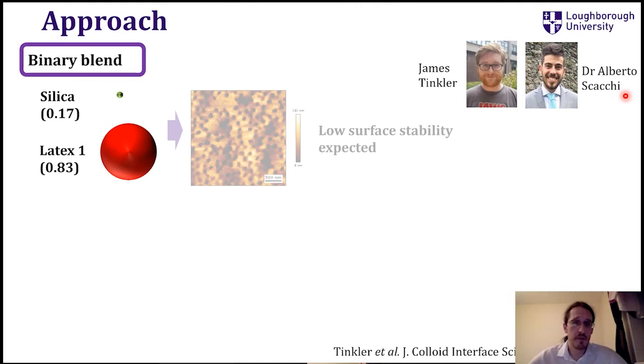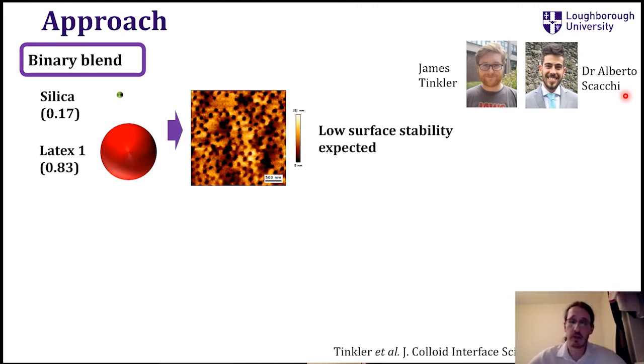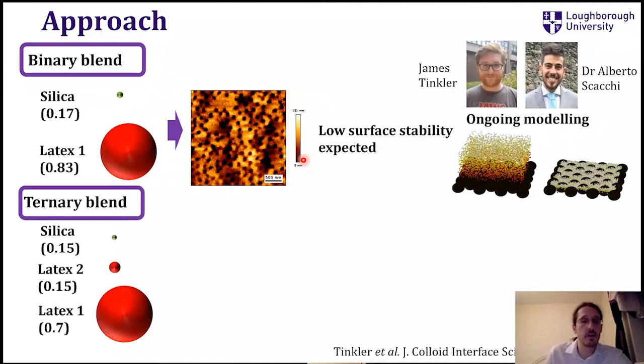And then we form a film with that, and we see a structure similar to the one that we saw with the zinc oxide. All that you see at the top there is silica nanoparticles. But we expect that there will be low surface stability because silica particles are hard. They don't bind to each other. So if there is abrasion, they will probably go away from the surface. So we said, okay, what happens if we add a second latex particle? Another soft particle, which will sit on top of the large one and will bind to the small silica particles. So we have small, medium, and large.